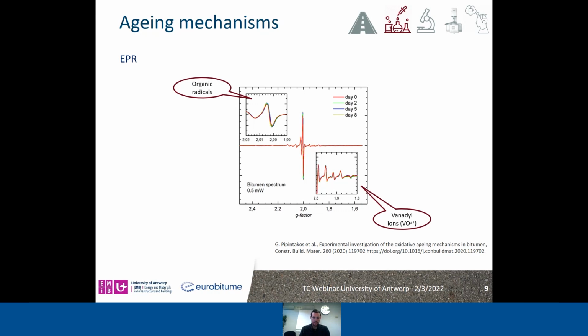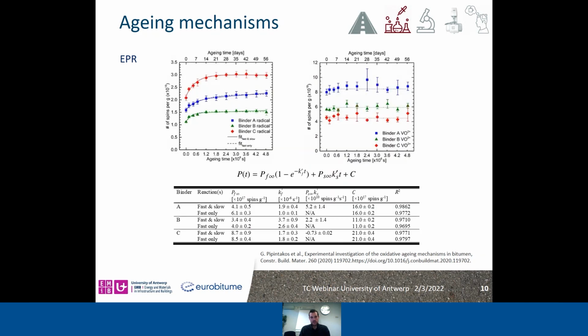This was performed via MATLAB, and we compared the simulations with standard libraries for spectra in order to find information about these radicals. After processing, we were able to plot on the left the number of spins of the organic carbon-centered radicals over time to have again oxidation kinetics of the organic radicals, and on the right the vanadium ions. First, we tried to fit it again with a fast and slow rate model. However, one of the binders even gave a negative coefficient, which is against such a model. Then a mono-exponential model of only a fast rate phase was used, and this fitted for all the binders.